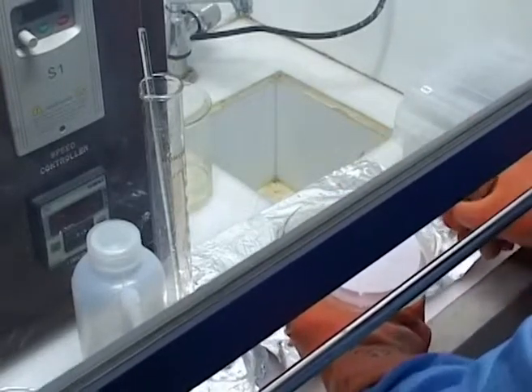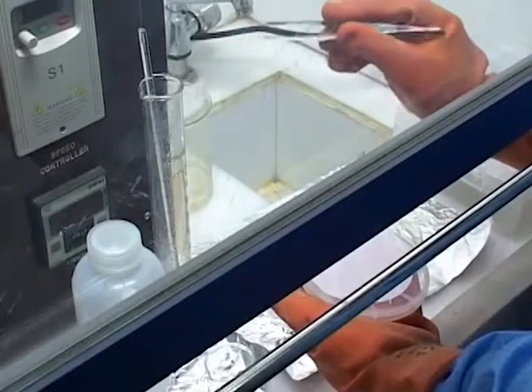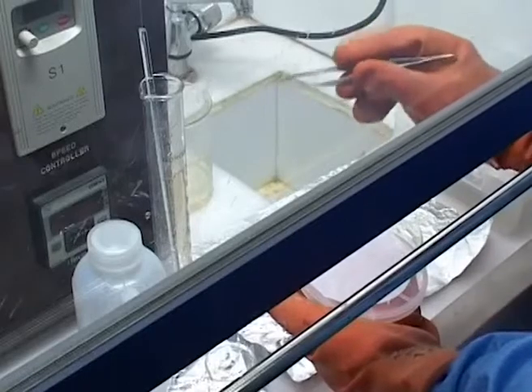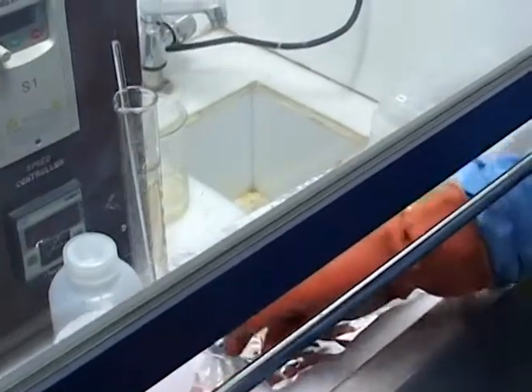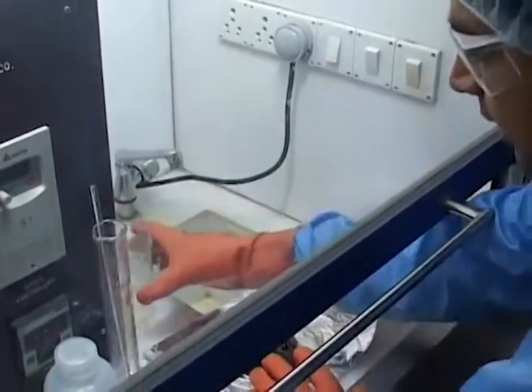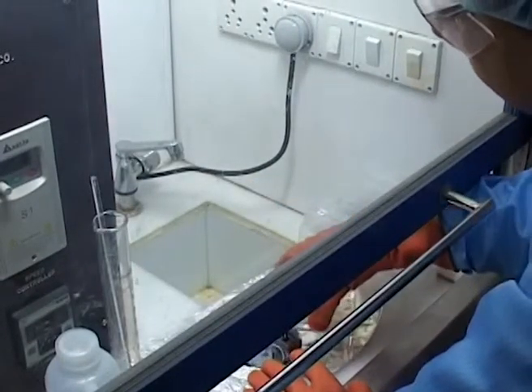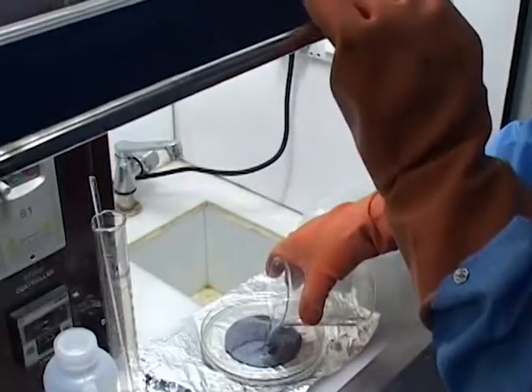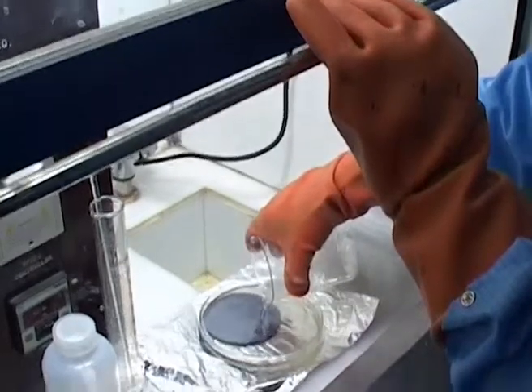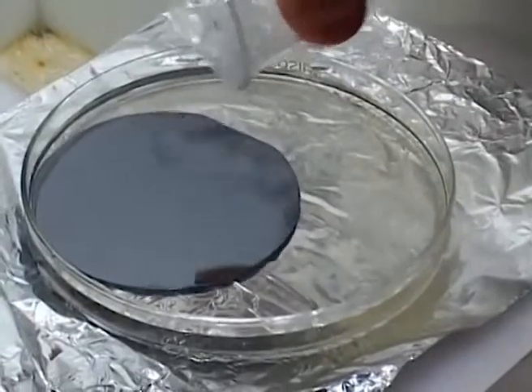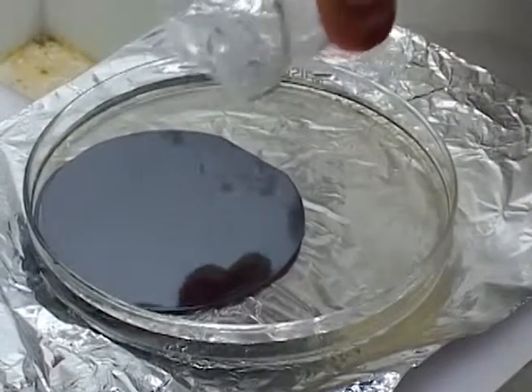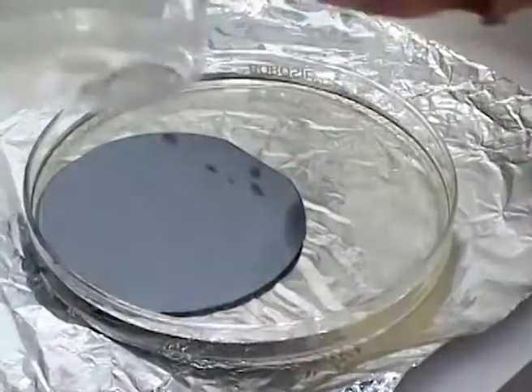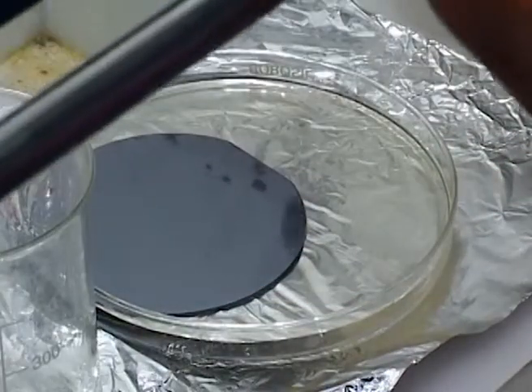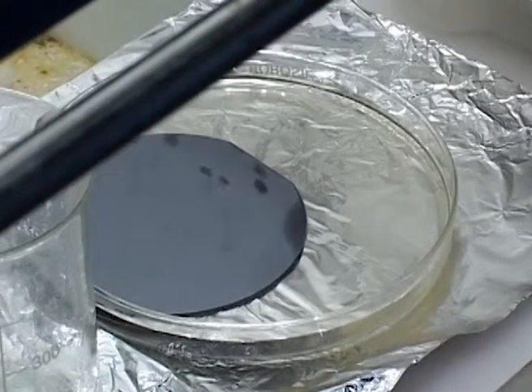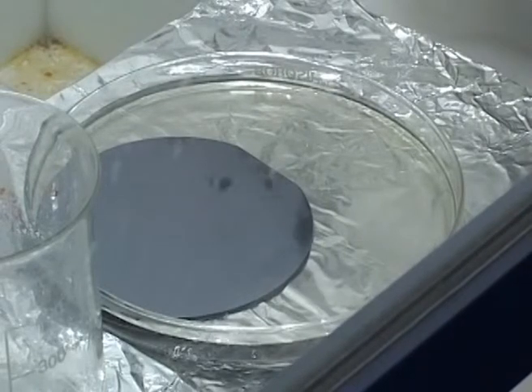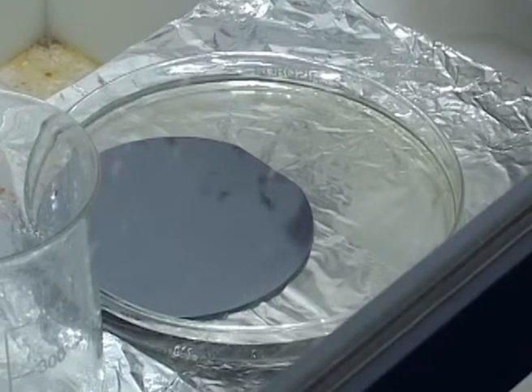Once we pour the piranha, we can no longer use this metal tweezer for handling the wafer. We'll have a separate Teflon tweezer for handling the wafer once it's out of the piranha for washing and rinsing. So now we slowly pour this chemical, the piranha, over this wafer. It is extremely hot, as you can see, and it also fumes as you pour it. Immediately, you can see the organic contamination over the silicon surface has been removed, and we store all these containers for later cleaning and use for different applications. Now we keep this closed and wait for about 10 to 15 minutes so that the wafer can totally get rinsed.